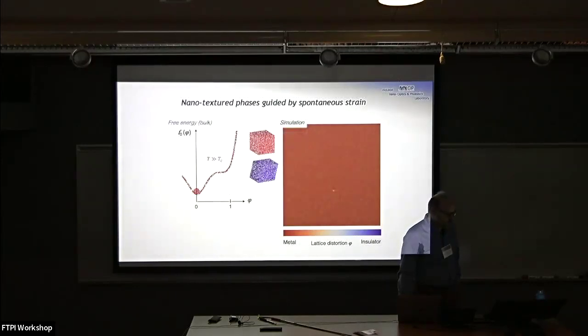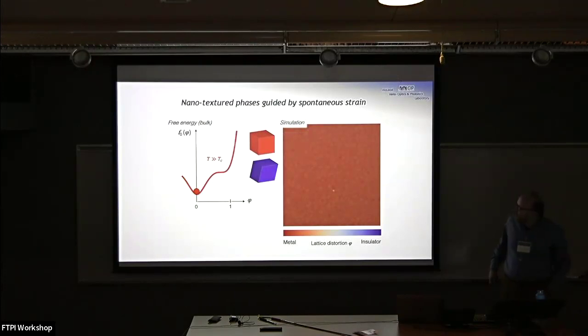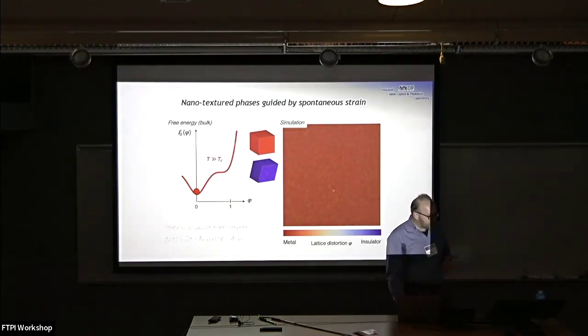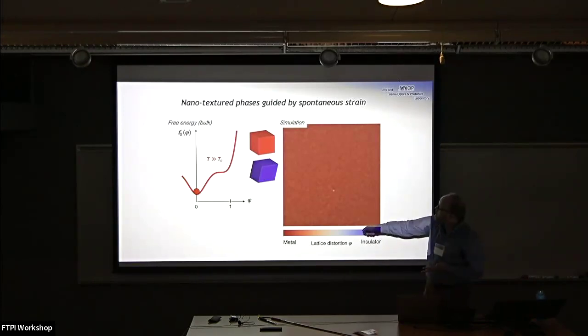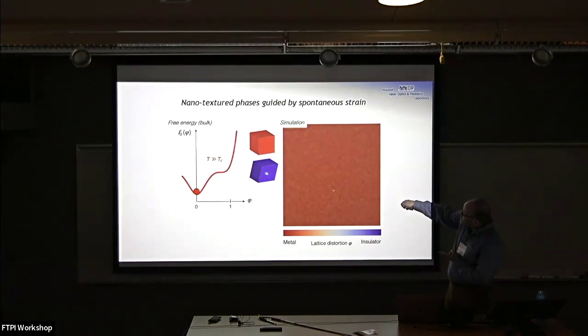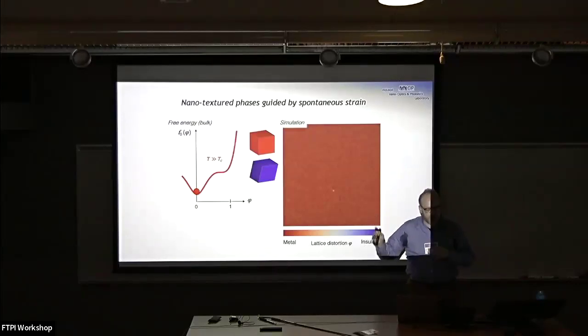But if we take those physics and apply them to VO2, we should remember that although we do have a first order transition with this double well potential, and I can sort of crank the temperature and change this double well potential with temperature. But let me also remind you that the order parameter, which might be non-zero in the Mott insulating state, might be zero in my Fermi liquid state, is accompanied by a distortion of the lattice.